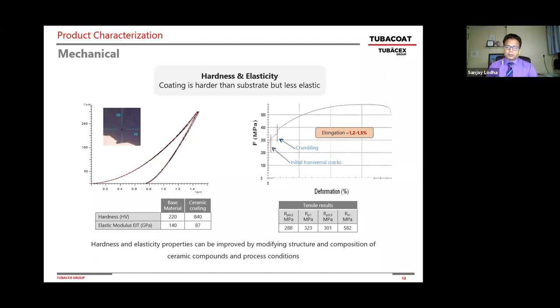And that cost is on my right side. If you look at the elongation, once you coat the tube, you can elongate up to 1.5%. And beyond that point, if you were to do physical bending or physical elongation, then there will be damage to the coating. So there is a price to pay. If you have a U-tube or a bend tube, first thing is to bend the tube first, and then we do the coating. So that can be done, but it cannot be done the other way. And that's an important point to remember. Next slide, please.